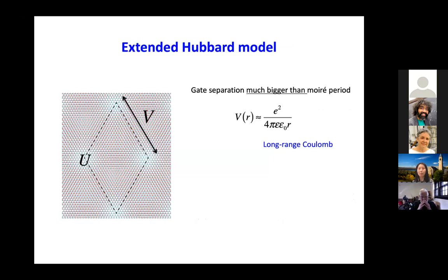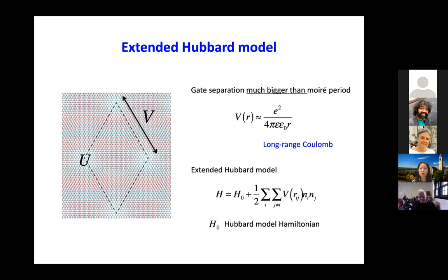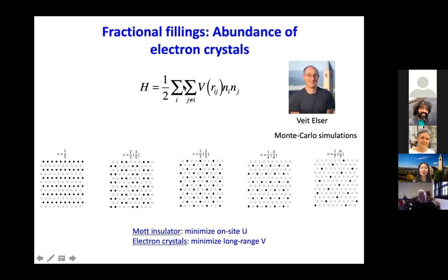Coulomb interaction by nature is long range. So in addition to the on-site Coulomb, the inter-site Coulomb interaction is also important, in particular when the gate is far away compared to the period. In those devices, the gate is about 20 nanometers away, and the period is only about 8 nanometers. So the longer-range Coulomb, like next-nearest-neighbor and nearest-neighbor interaction, can also be important. We have to consider those extended Coulomb interactions in the Hubbard model. When the filling factor is smaller than 1, and when V is bigger than T, we can forget about U and T, because in that case U is just infinity. It tells us you can very rarely put 2 particles at the same site.